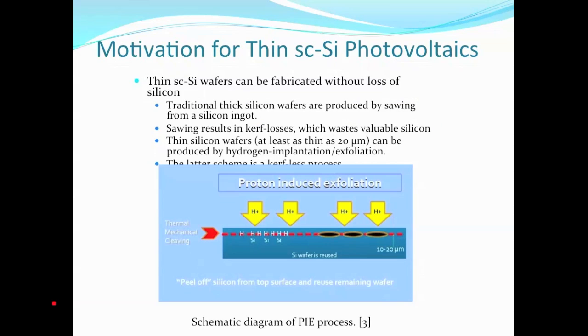Another reason is that thin silicon wafers can be fabricated through a lossless process. So traditional thick wafers are created by sawing from a silicon ingot. The sawing induces losses known as kerf losses, which wastes our valuable silicon. But thin silicon wafers can be fabricated with a process that doesn't waste any silicon. So one way of doing this is proton-induced exfoliation. So protons are embedded into a certain depth in a thick silicon wafer. The protons then turn into hydrogen gas, and when the substrate is heated, the top layer will peel off. So we can continually peel off thin silicon wafers from a thick silicon wafer, conserving silicon in the process.